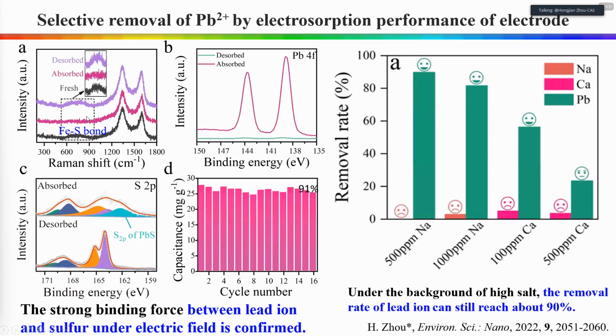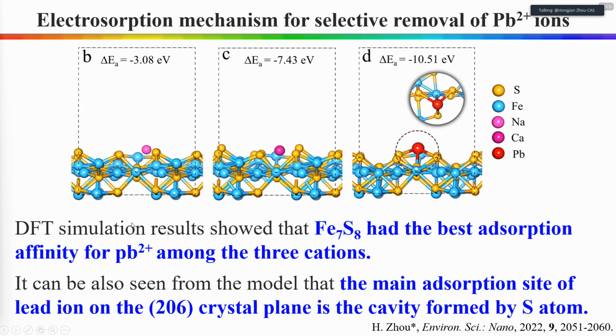We try using XPS characterization to figure out the mechanism behind it. In the XPS result, we can find the strong bonding force between the lead ion and the sulfur under the electric field is confirmed, and also under the high background of high salt, the removal rate of lead ion can still reach about 90%. So it has selectivity. We try using DFT simulation to prove the selectivity mechanism. We can find our material has the best adsorption affinity for the lead ion among the other cations, for example, sodium, calcium, and so on. And we can see that the main adsorption site for the lead ion on the 206 crystal plane is the cavity formed by sulfur atoms.